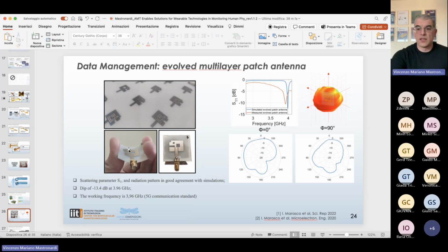So this is a picture showing the results of our device that shows high flexibility. And we tested the antennas in order to measure the scattering parameters and the radiation pattern, which is in very good agreement with the results we achieved by theoretical simulations, showing us that the antenna is able to work at a frequency of about 4 gigahertz, that is in the 5G communication standard protocol.